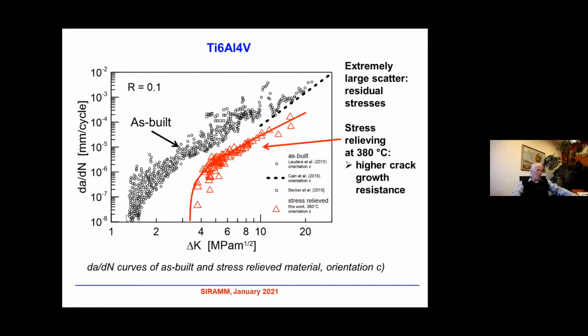The main problem is, however, in the threshold values. The threshold for crack propagation in the as-built material is shifted towards very low values, nearly 1.3 megapascal meter to 1/2. What does it mean? When I have a small crack in this as-built material, it propagates much more easily than in this case. So we can see that only the stress relieving resulted in an improvement of the as-built material.